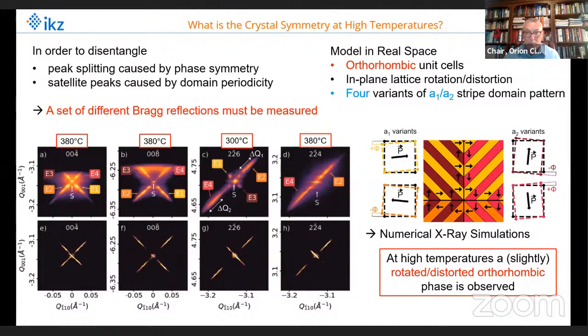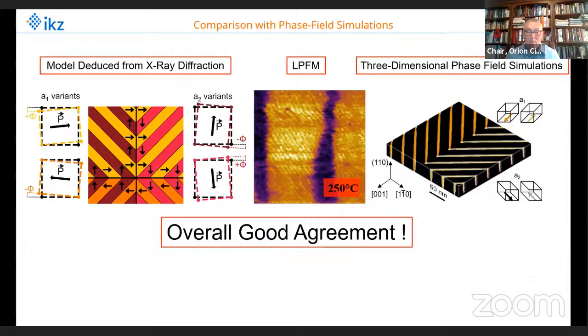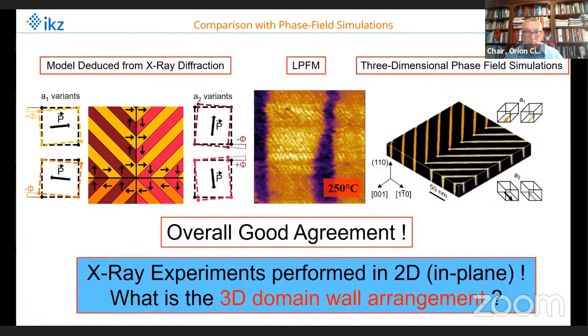And when we put this model into numerical X-ray simulations, we end up here at the left side, to the bottom, with these 4 simulations, and they fit quite nicely to the experimentally observed diffraction pattern. So indeed, we have at high temperature a slightly rotated orthorhombic phase. Okay, we can also compare this with phase field simulations. On the right-hand side, we see that also in the 3-dimensional phase field simulations, we observe an orthorhombic phase with A1 and A2 unit cells, and we observe, by the way, also different stripe domain variants, quite similar to the variants we observe in the PFM image in the middle. So we have an overall good agreement between simulations and experimental data.